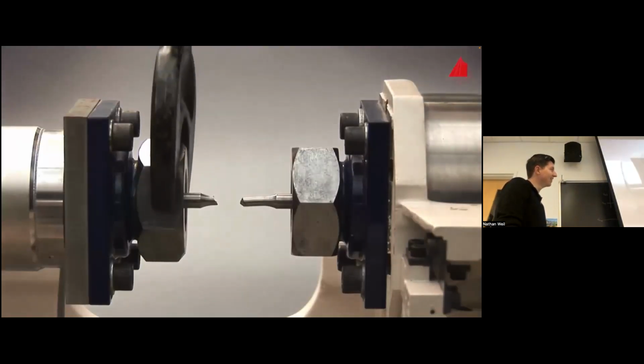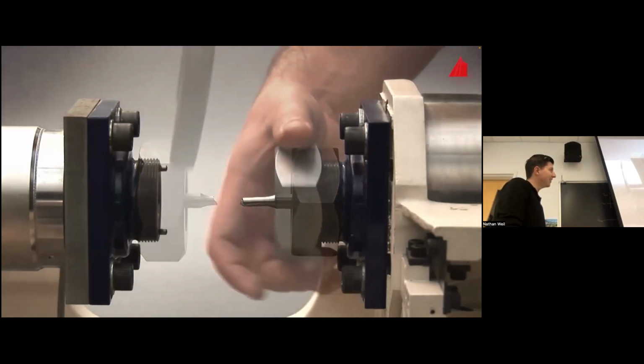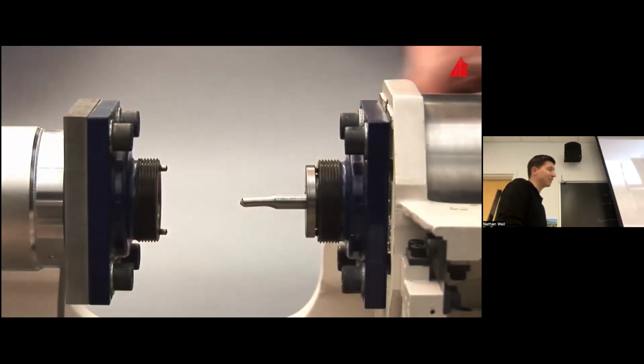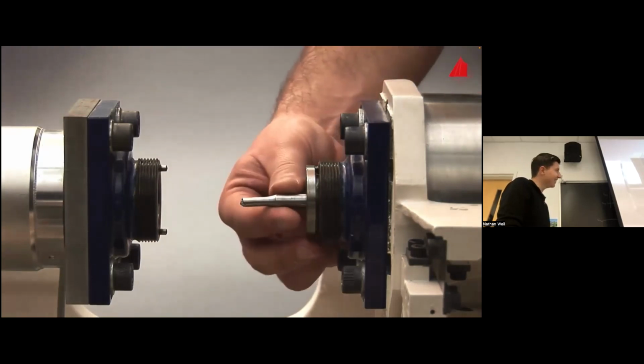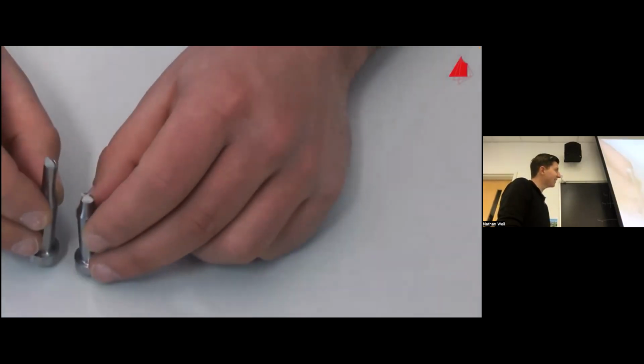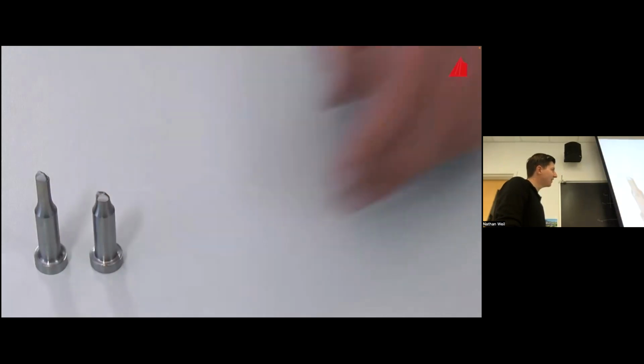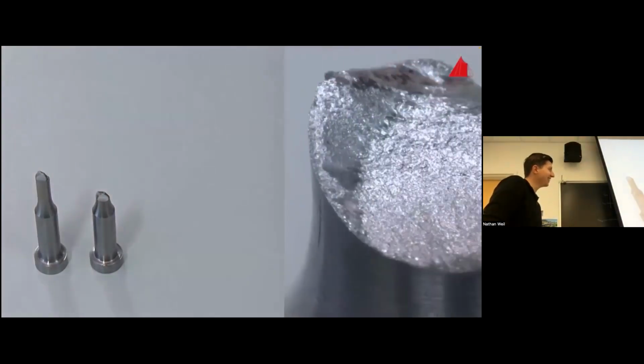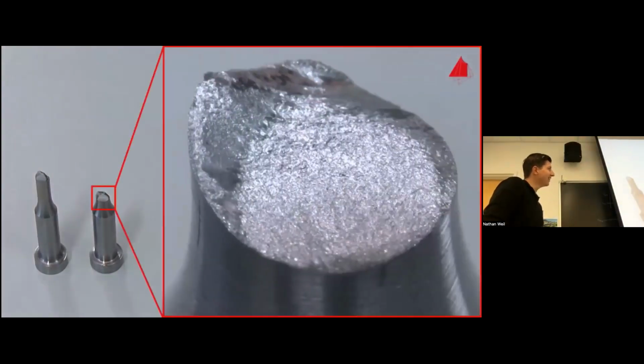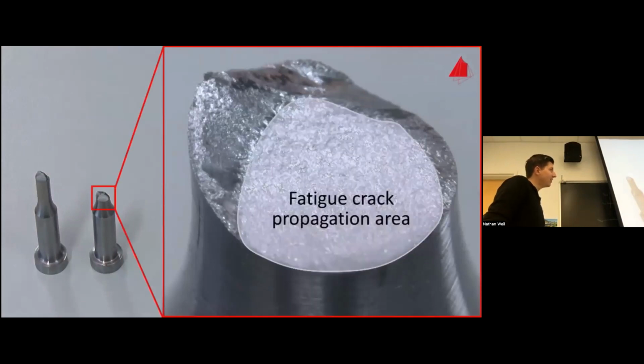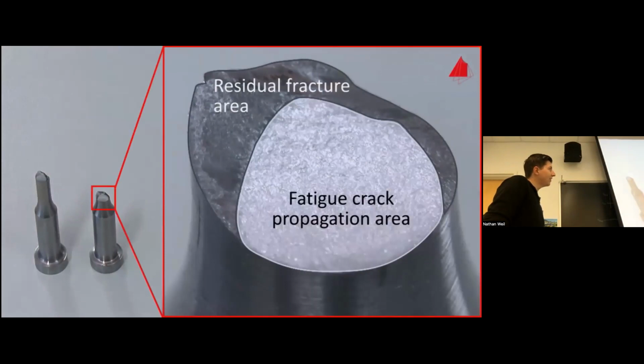The material tester removes the fragments cautiously and inspects the fracture surfaces. At first glance, the fracture surface looks unimpressive. A closer look reveals two regions: the rather dull, predominantly flat fatigue crack propagation area and the rough residual fracture area. The residual fracture area results from the final catastrophic rupture.